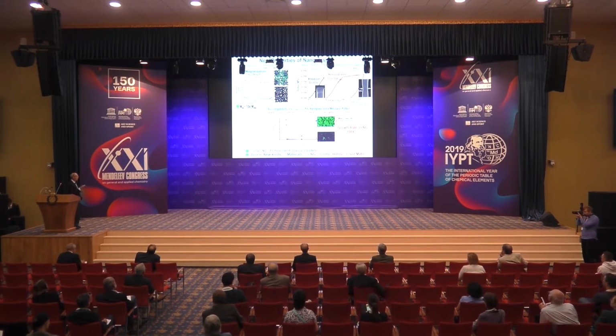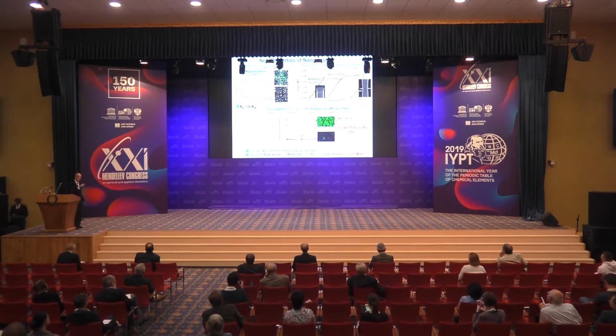In fact, if you would go back to the iron 90 scandium 10, we can go from a paramagnetic to a ferromagnetic state. Here we just increase the magnetization. A second effect, which I want to show here, is the surprising effect of the biocompatibility. This was a titanium zirconium glass in the form of a nanoglass and in the form of a melt-spun ribbon. And when we put cells, osteoblast cells, these are model cells, on the surface of the nanoglass, they grow a factor 100 times faster than on the surface of the same, chemically same material, but as a melt-spun ribbon.